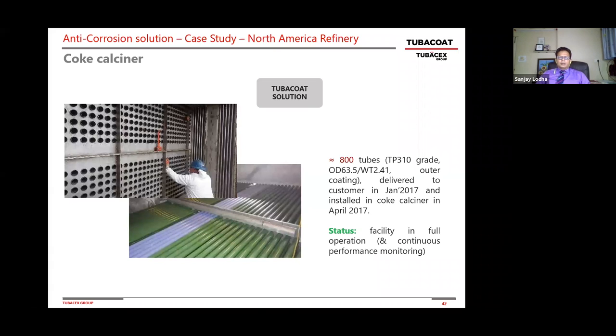So they went with 800 TP310 tubes, and as you can see, there are two different color schemes of the TUBACOAT technology. It's not just because we like different colors. They were designed for different temperatures. As I said, we customize these tube coatings for different applications, different conditions, and different temperatures. Some of the tubes you see were designed for 700 to 750 degrees Celsius and some for another 20 degrees higher. They were installed in April 2017. Next slide.